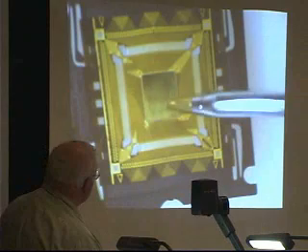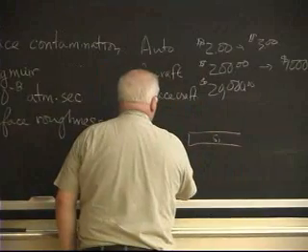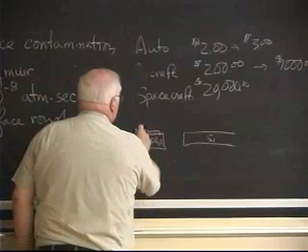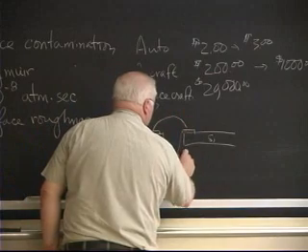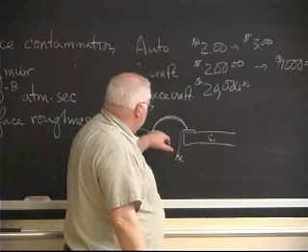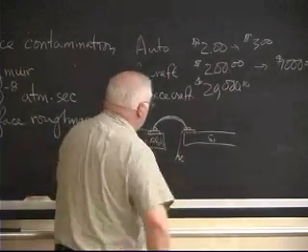this would be the silicon chip in here in the center, and these are the bonds going around it. This has 400 inputs and outputs, so it has to have 800 bonds on one chip. If this is the silicon chip sideways, and this is your substrate, which would be aluminum oxide with a little copper pad, or typically might be a gold pad, this thing will have a little aluminum pad deposited on it. They will run a gold wire about 25 microns, 1/1000th of an inch, and they will just squeeze it into the surface. And it'll make a little clip like that. We'll talk about it later.